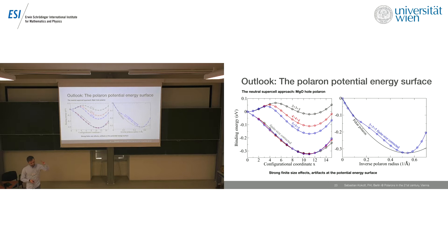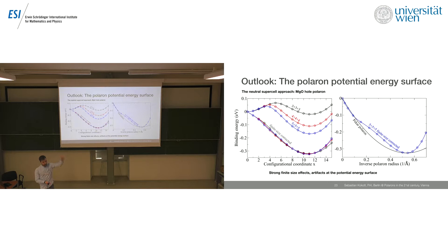Yes, that's correct, and this is a little bit more tricky. For epsilon infinity, to get it for the hybrid calculations, I used a charged oxygen vacancy. From the tail you can also derive the dielectric constant. For PBE I used a DFT method. Basically epsilon zero is obtained if you calculate the slope of this extrapolation of a relaxed charged vacancy, and for epsilon infinity we used the unrelaxed vacancy and extrapolated from that.